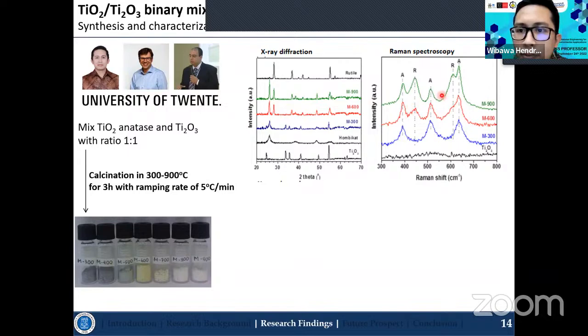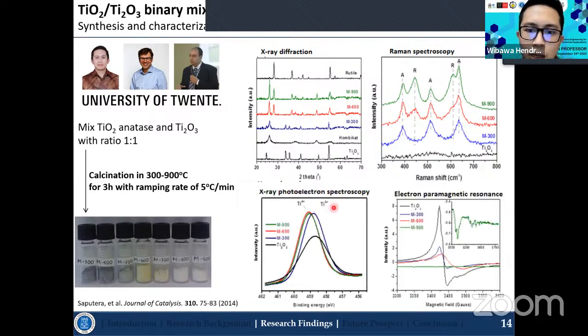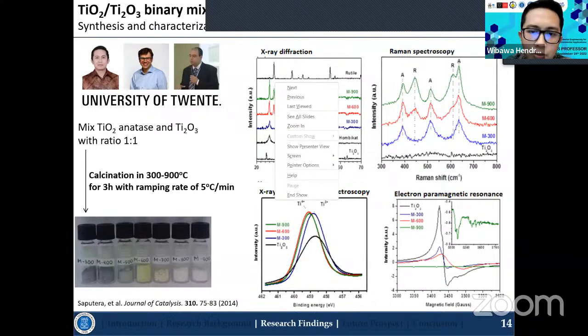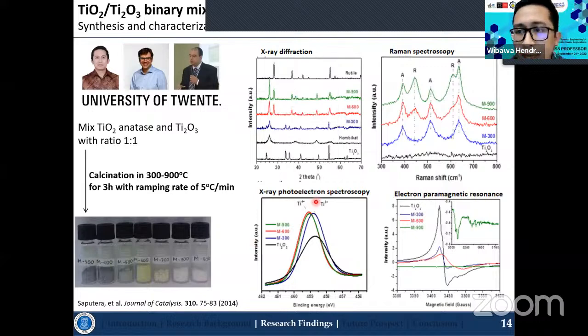And it's confirmed by the Raman spectroscopy as well. At M300 there is no rutile phase appeared, but for the 600 and 900 calcination temperatures, the rutile phase is generated. And also, we try to confirm the presence of the defects on the structures, which is the titanium 3+, and it is confirmed by using the XPS, X-ray photoelectron spectroscopy, where the titanium 3+ appeared on the surface of the catalyst.